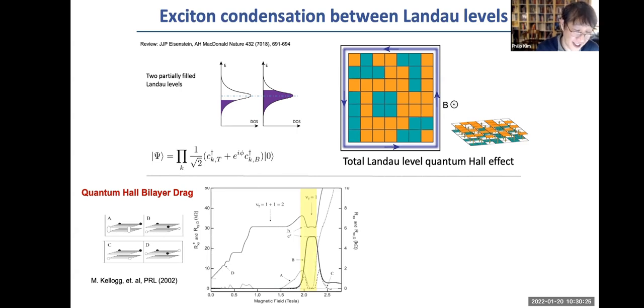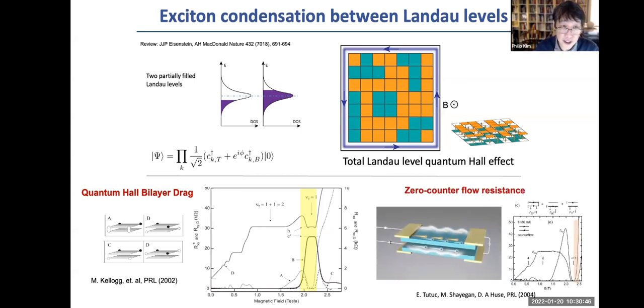An example is shown here from Jim Eisenstein's group at Caltech in the late 90s, early 2000s. The group beautifully showed that indeed the partially filled Landau levels can form one entire full Landau level, and a strong Coulomb drag effect appears in these two layers, indicating that the two layers got coupled. A few years later, a few other groups, including Mansour Shayegan's group at Princeton and Klitzing's group at the MPI in Germany, showed that it's not only that the two layers are strongly coupled and show this Coulomb drag effect.